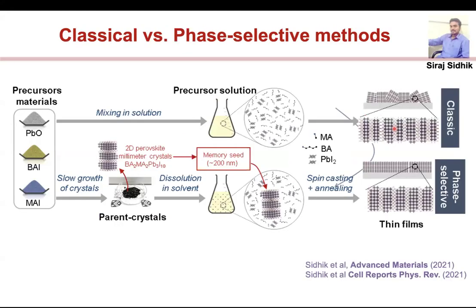And so, we've been thinking about how to go about this. And one of the approaches that we took was quite different. What I'm showing you is basically these precursor materials that people use for making the 2D perovskites. And what they normally do is they take these precursors, they mix them in solvents, and then they cast films of this. And we call this the classical method. This is what has been used in the literature.